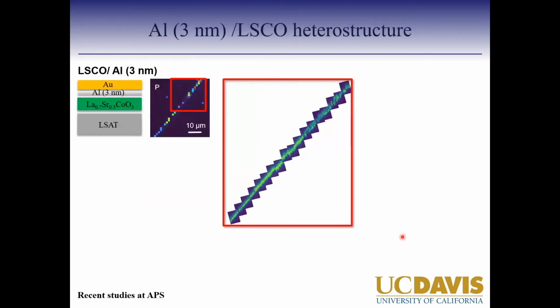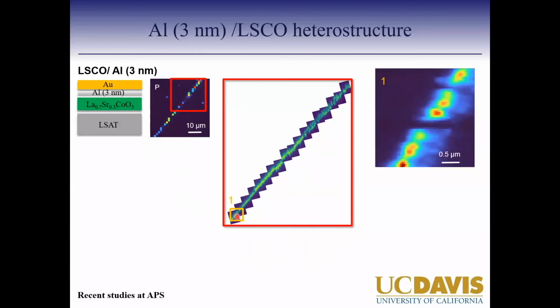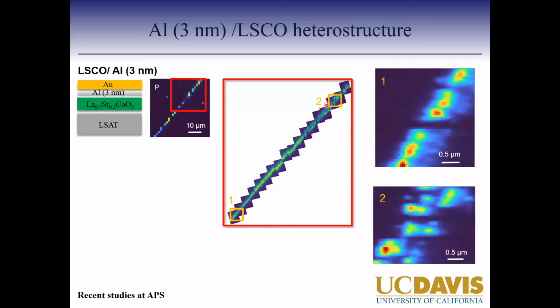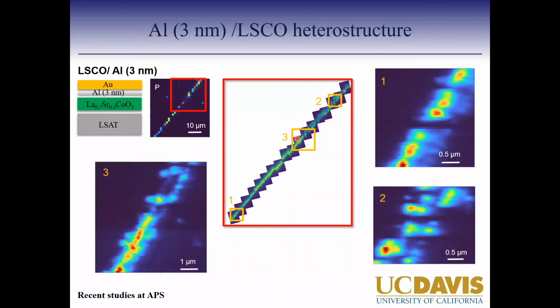So we also looked at an aluminum 3 nanometer LSCO structure, so another getter layer, to see whether it's unique to gadolinium or not, so that was one question we had. So we looked at a different layer, and we see the same thing. We see these filaments at almost a 45-degree angle, and we can look at different parts of these filaments. So here, this is this one area, and then we can look at a second area where we almost see 2 different filaments in parallel, and then in the center right here.